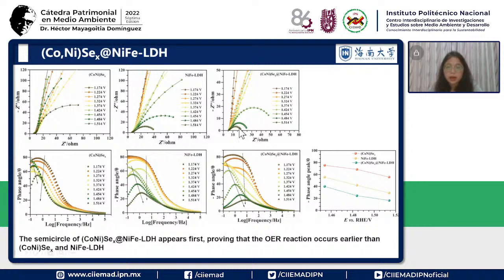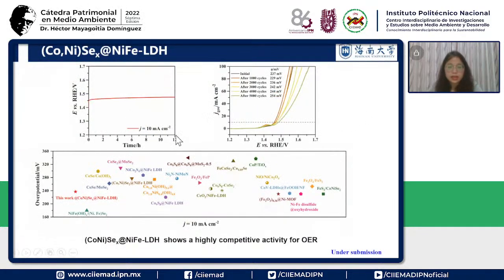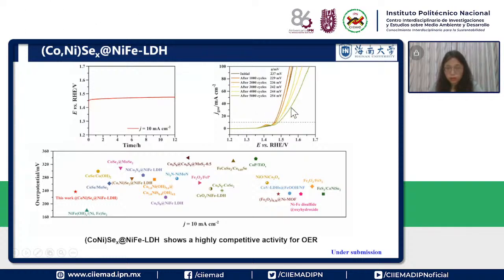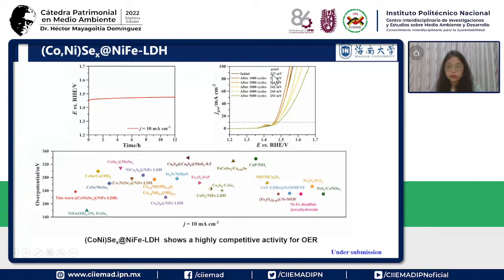It appears first compared to the other two, and that means this composite occurs earlier than the other two samples to catalyze the OER reactions. And then we tested its stability after 12 hours. It is almost stable, not changed much. And then after cycling 5,000 cycles, the overpotential only increased from 227 to 254.